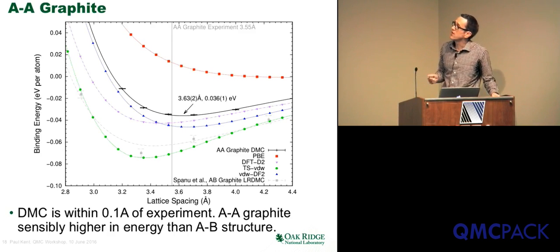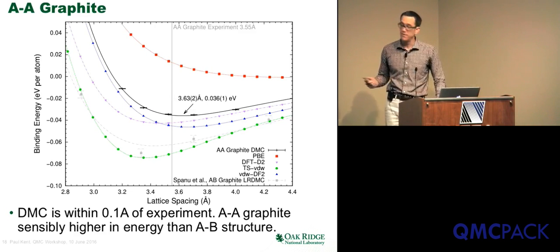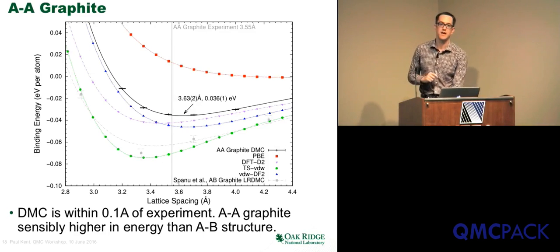And we see various trends in the DFTs. The self-consistent functionals are really behaving best, whereas the non-self-consistent version of Tkatchenko-Scheffler is actually significantly overbinding the system. So that was a surprise. They know about that, and they fixed this behavior in the self-consistent version.